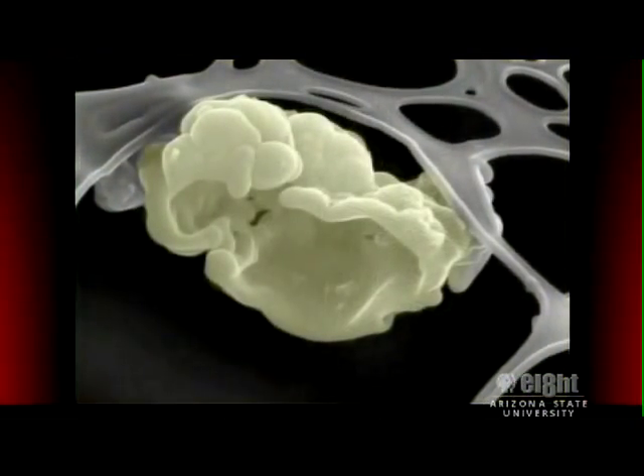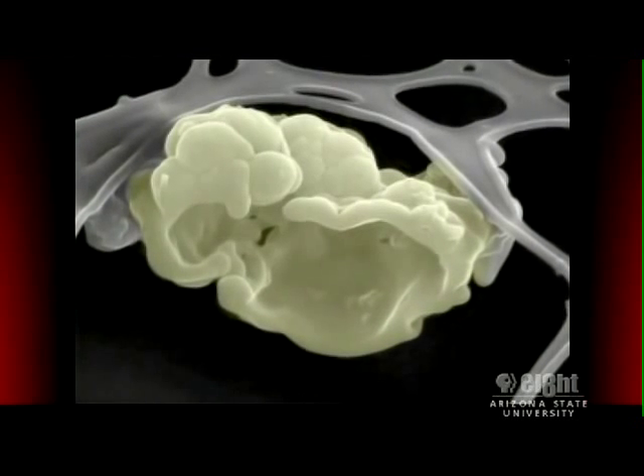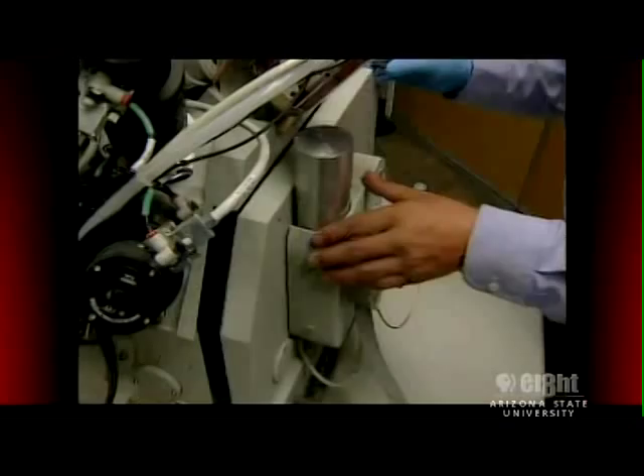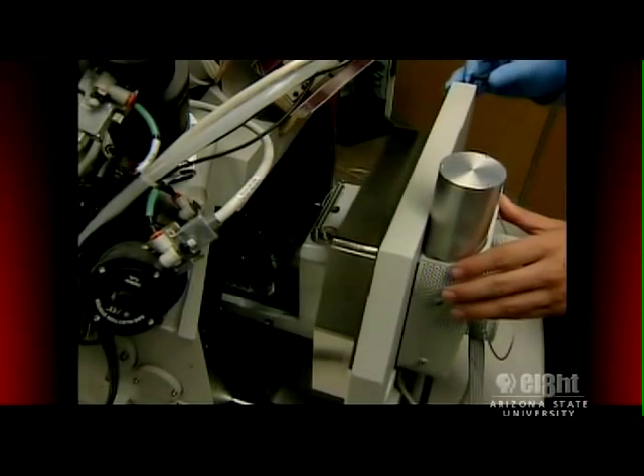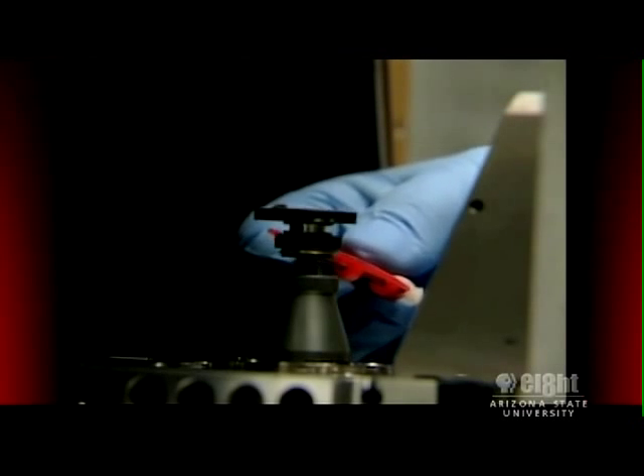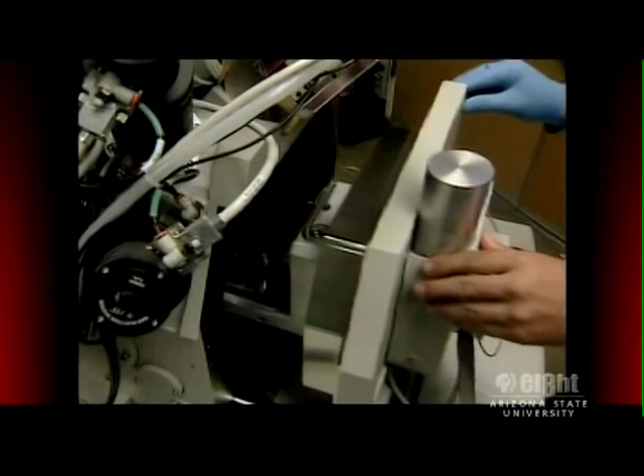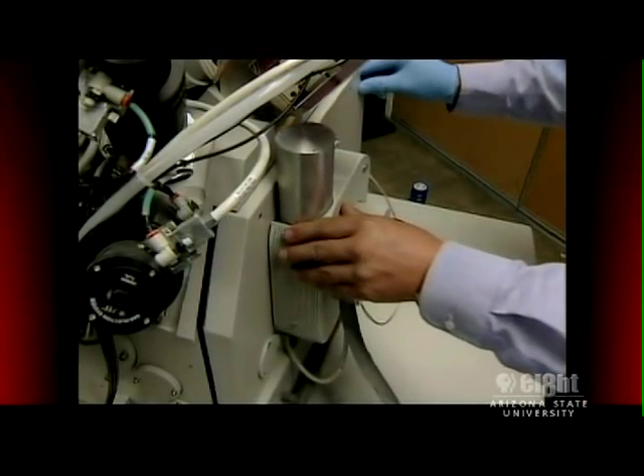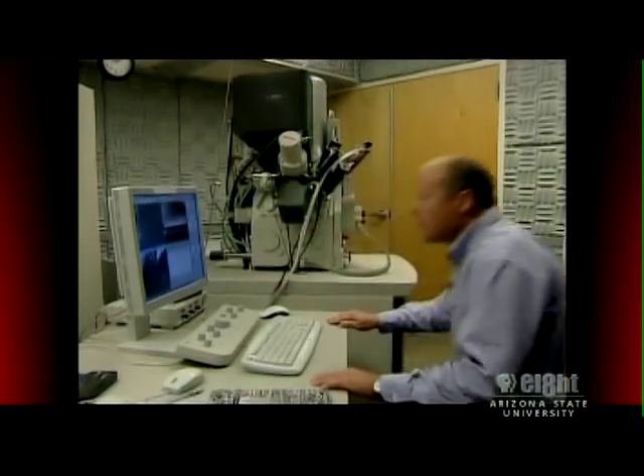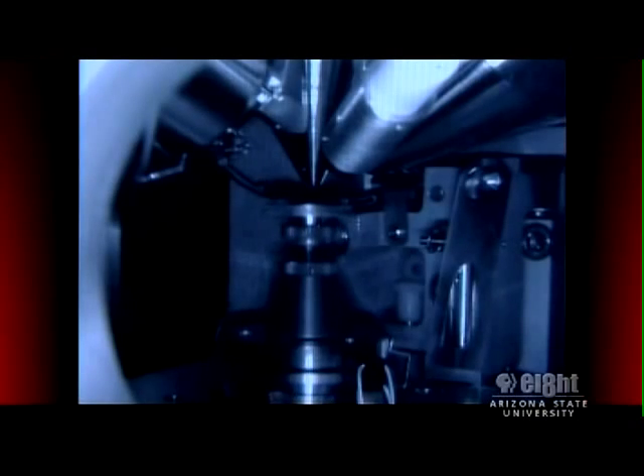The examination of some materials called carbonaceous nanoglobules — or as Garvey refers to them, space globules — is not without interesting challenges. It turns out that these things are very sensitive, since they're so hydrogen rich, so they change when we look at them too long. Just by looking at them in the electron microscope, you see them shrink. They're losing hydrogen under the electron beam. So probably the next and most difficult thing that we're going to do is determine their structure.